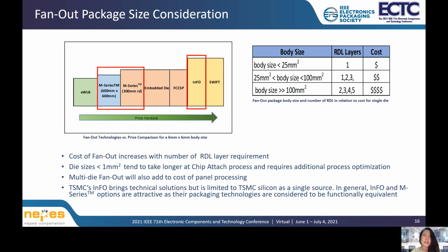Larger body sizes, I would say above 100 mm squared, for example, like AI, networking, or high-performance computing, are best served by chip-last platforms. Although chiplet-like processing utilizing chip-first process is on the horizon. Key drivers for fan-out are body size and number of RDL layers. It is possible to have a body size less than 25 mm squared with 2-layer RDL. However, the cost of the fan-out package will also increase with the added RDL processing.